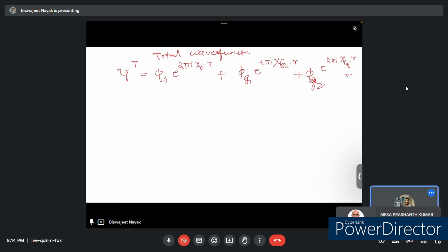So for solving this wave function, we have to consider one diffracted beam G. So we make a two beam approximation. Here one diffracted beam is G and another diffracted beam is O.